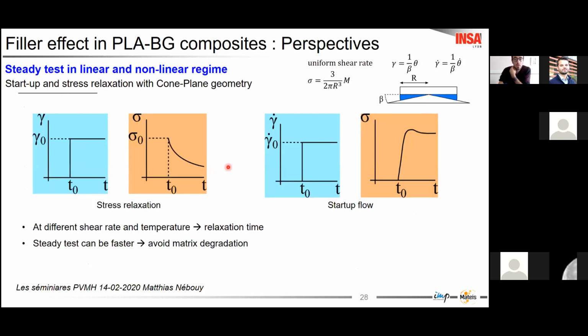In order to reduce the experimentation time and simulate the thermal degradation behavior, maybe a steady test in linear and nonlinear regime could help obtain results without huge degradation in the matrix during experimentation. Here I show you a possible example of a study to do with these evolutive systems.